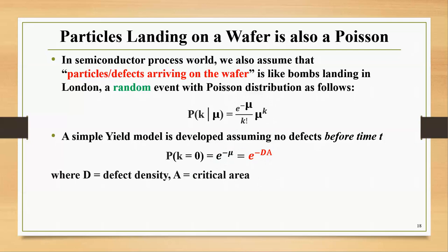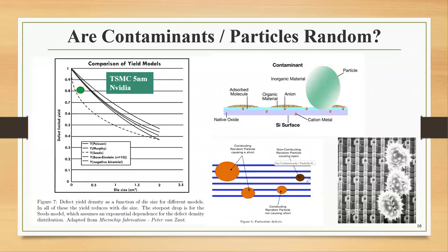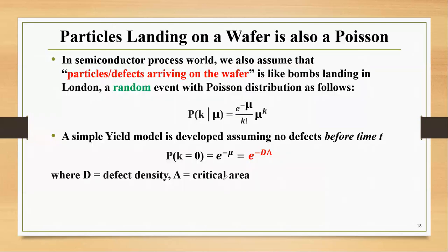Remember, just a quick review. If your A is very small, right? If your A is sitting here, then this defect has no effect, right? If your A is very large, then this defect has an important effect. That's what we keep telling everybody, that the size matters. So these all are a function of die area. So keep that in mind. So this is the most famous and the most rudimentary fundamental formula that the first generation of yield analysis used to predict yield. It's just a simple statistical exponential.